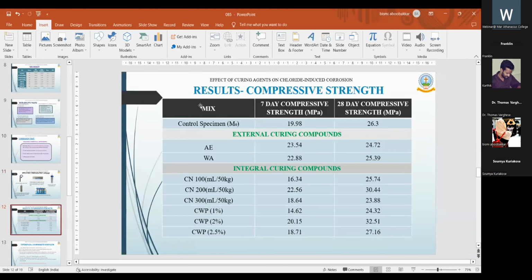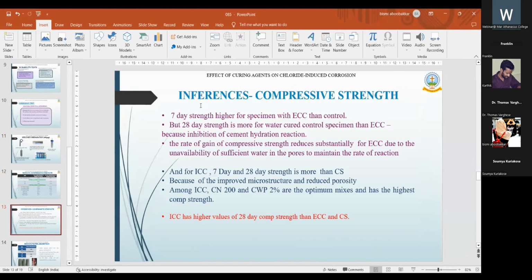These are the results of the compression test. From that, these inferences are obtained. The 7-day strength is higher for the specimen with external curing compound than the control specimen, but the 28-day strength is more for the water cured control specimen than external curing compound because of the inhibition of the cement hydration reaction within the concrete, and the rate of gain of compressive strength reduces substantially for external curing compound due to the unavailability of sufficient water in the pores to maintain the rate of reaction.